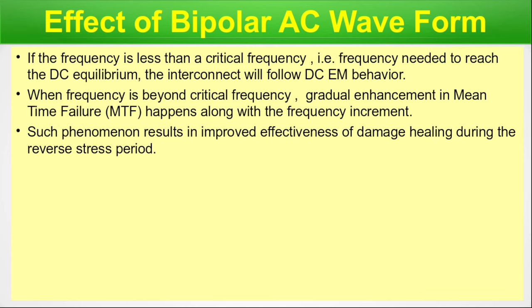Such phenomenon results in improved effectiveness of the damage healing due to the reverse stress period. In an AC, when the swing is in the opposite direction in the two parts of the half cycles, the direction of the electron wind is completely opposite. So in one case, the electron will try to create a void, and in the other part of the swing, it will try to heal it. This is the nature, because the direction of the electron wind is completely opposite, and hence the momentum transfer to the metal ions is also in a different direction. So if that momentum transfer is in a different direction, then definitely in the first half of the swing or in the positive swing, the void, whatever amount it was getting created, in the second half, that means the opposite swing, those voids will be healed a bit.